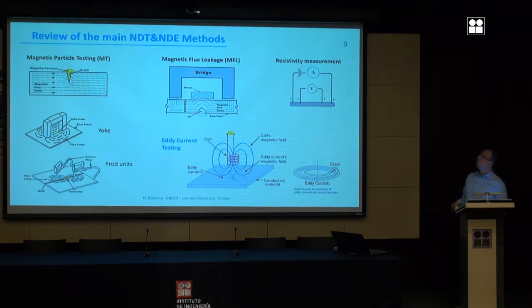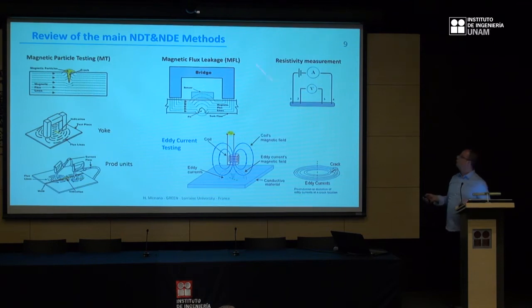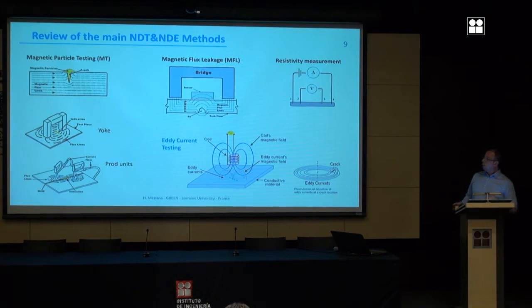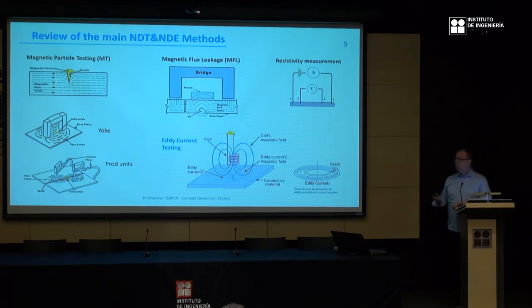Of course, when it concerns conductive material, we have the four-point measurement to characterize the conductivity or even the presence of a flaw locally. And the most common one is eddy current testing. In eddy current testing, we have a coil, a sensor which is generally a coil fed by an alternating current. This coil will create an alternating field. If you put this coil above or near a conductive plate, the alternating field created by the coil will create eddy currents in the tested piece.